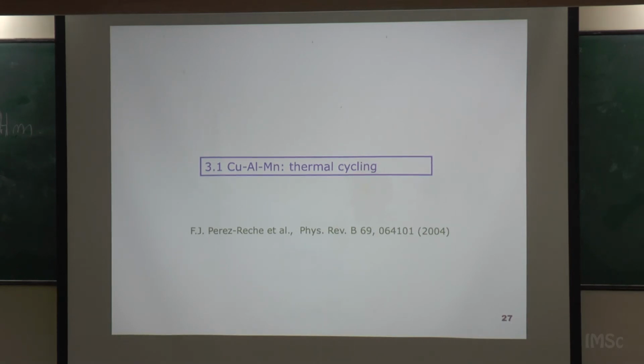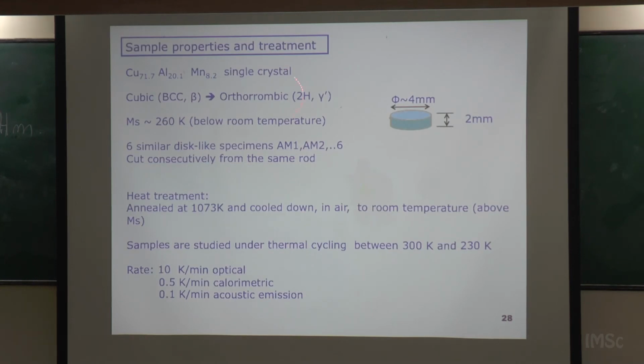So now I have some examples, but let me show you some, maybe the ones that are more interesting for people in the materials field, doing this kind of analysis. This is something that we did many years ago, which was just studying the martensitic transition induced by temperature. So here we change the temperature, we induce the transition, and this is a copper aluminum manganese alloy, okay? I won't go into the details. It has this transition from cubic to orthorhombic.